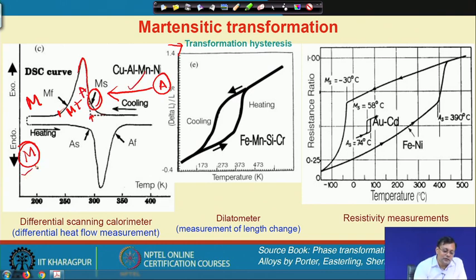However, if we start with the martensite heating, then it needs some extra energy to transform. So, here we call it austenite start. The suffix S stands for start and F stands for finish. So, here also S stands for start and F for finish. Here we have martensite plus austenite, and here all the martensite has transformed into austenite. Almost at the peak temperature we can assume that 50% of the transformation from martensite to austenite has completed.